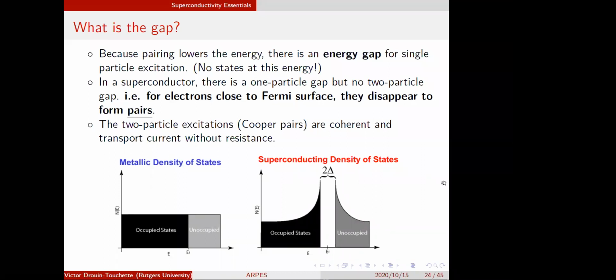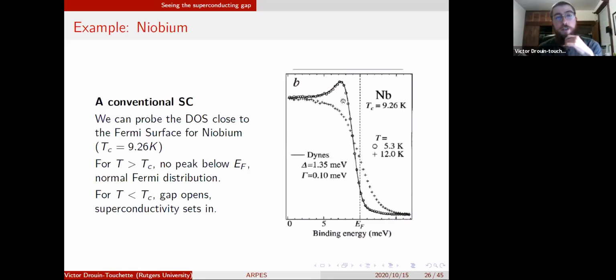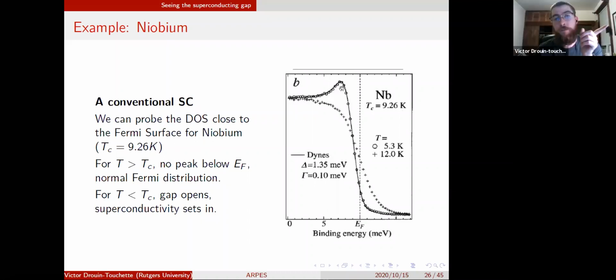And this peak is shown in the later experiment that you were showing, right? Exactly. So you're really supposed to see such a gap. So not seeing this gap is very different. If you saw the same feature but you didn't see the gap, it'd be puzzling. There's supposed to be this peak here because that's the condensation of all of these lost states. All of this lost density of states needs to be piled up somewhere. Not seeing that is usually the signature of a pseudogap. So yeah, okay. Thanks.